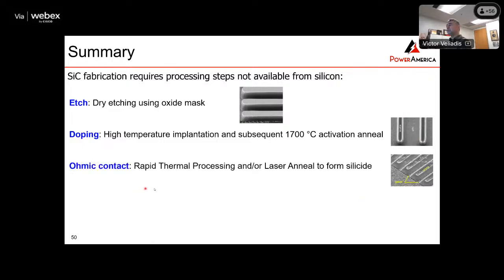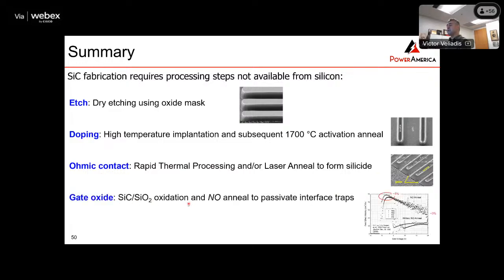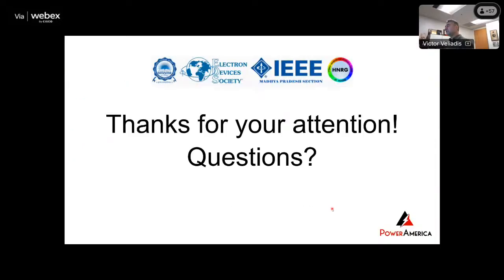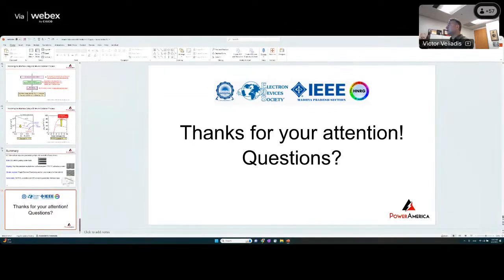We talked about the ohmic contact formation that can be done with a rapid thermal anneal if you're at the stage of making the contacts in the front of the wafer, or do a laser anneal to form the ohmic contact in the back of the wafer at the very end of the process. And then we talked about the issues with the gate oxide. The silicon carbide oxide surface is of very low quality, has a lot of traps. You do a nitric oxide anneal in order to improve the mobility and passivate the interface traps. And as I mentioned, there's a lot of work in this area and new experimental methods to improve the gate oxide. And with that, I want to thank you for your attention. And I'm here to take any questions you might have.